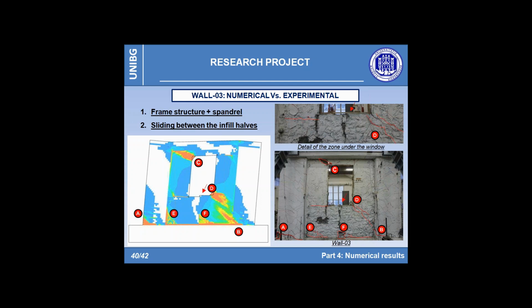As usual, close to the opposite corner of the window, letters C and D, important damage areas can be recognized, also clearly highlighted in the experimental view. Finally, also in this case, the sliding movement between the infill halves is correctly modeled, as shown in the upper image, where a detail of the window is reported.